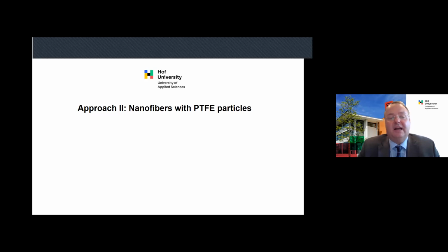Because, as you already know, if you have dust particles in the air, there is a certain friction between the dust particles and the air, and therefore you have the so-called effect of triboelectricity. That means it is an electrical charging process by the friction between the air and the dust particles. And therefore, a lot of particles in the air are charged with electrical charges. And if you also have charges on the PTFE particles, then you have attraction between opposite charges, of course. And therefore, if you implement these PTFE particles in the nanofiber network, you can increase the collection efficiency.